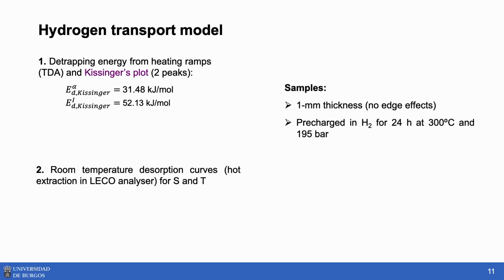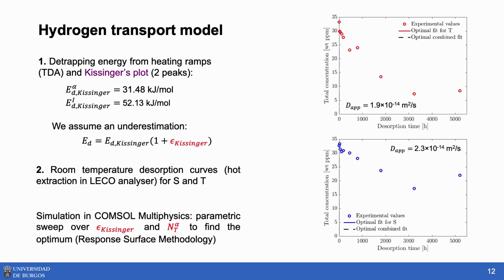Finally, we are fitting the values of the trapping energies and the density of defects in ferrite. All of these steps have been performed at the University of Oviedo. The first step that we have done is to find the trapping energies by fitting the TDA profiles. And we identify 2 main peaks. One peak, the lower energy peak, was attributed to the defects in ferrite, and the strongest to interfaces. I'm putting this subscript Kissinger because actually we don't trust the Kissinger results. This plot, that maybe you are familiar with, we have demonstrated, and many authors have numerically demonstrated, that the Kissinger plot is always underestimating the trapping energies, especially under certain conditions.